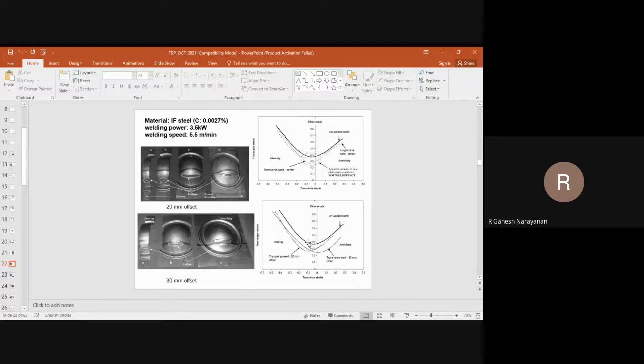In a component, the location of weld is very important because the weld should not be in a location where failure is going to happen. See, in any component, failure is going to happen in a particular location. Of course, you cannot predict failure because it depends on the material heterogeneity, how it develops, all that. But let us assume that failure is going to repeatedly happen in one particular location. Then it means that the weld should not be at that location. It has to be away from that.